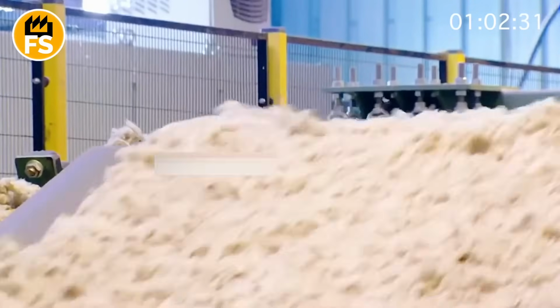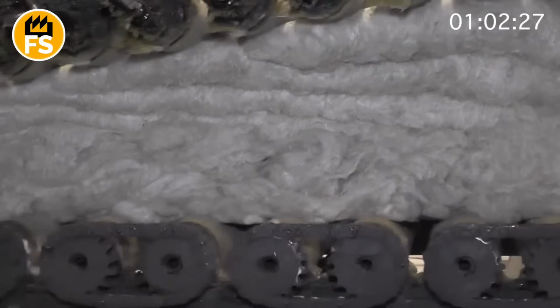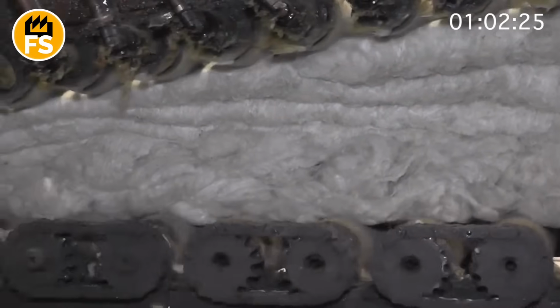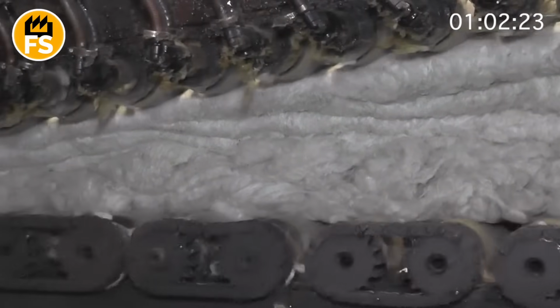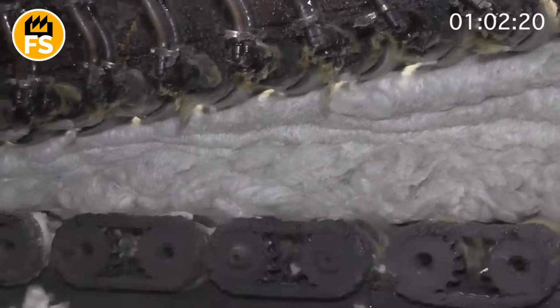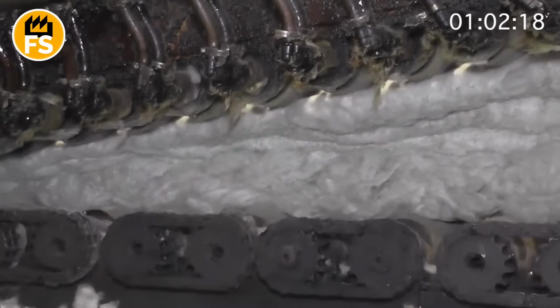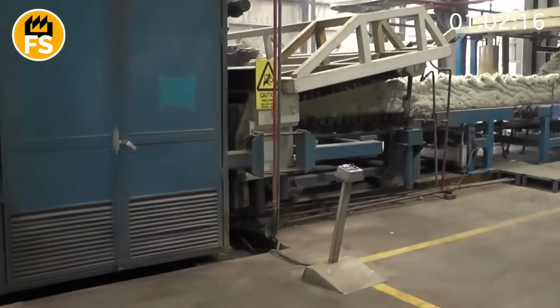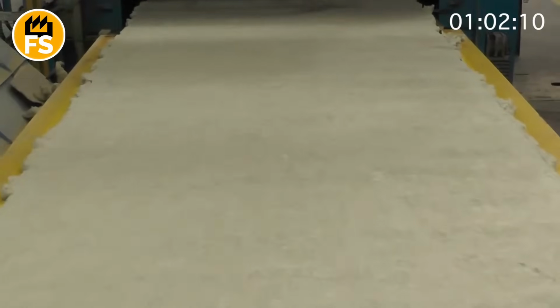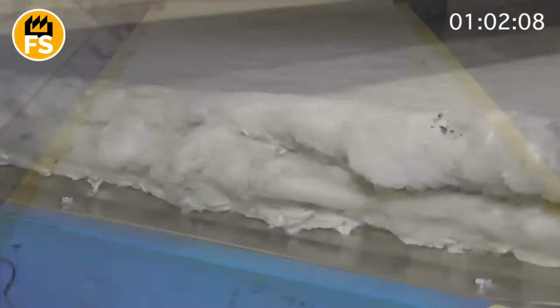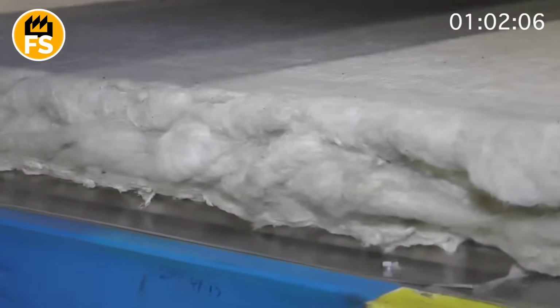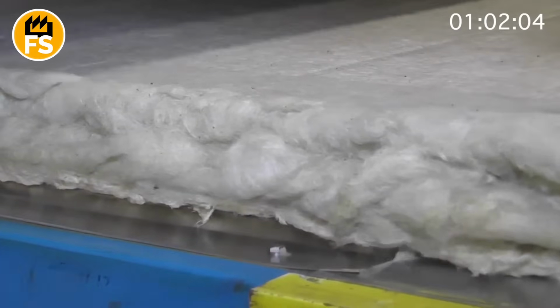This cloud of glue-soaked fibers flies on and enters a deposition chamber. At the bottom of this chamber is a wide, moving conveyor with a perforated belt. Powerful fans draw air from under the belt, creating a vacuum. This airflow pulls the fibers down and lays them evenly on the conveyor, forming a thick, fluffy mat.